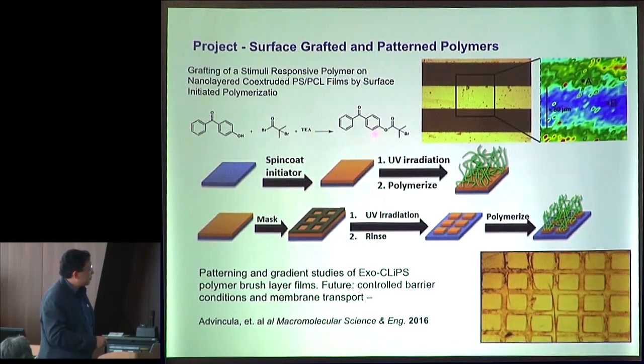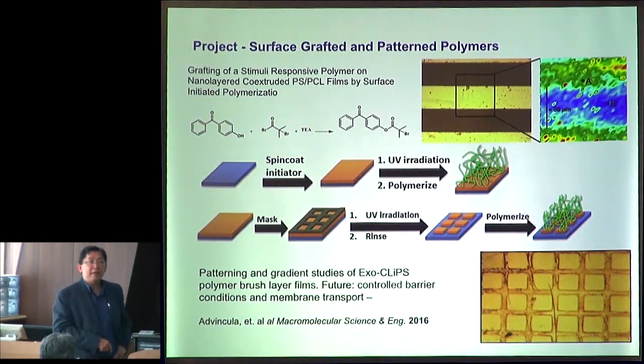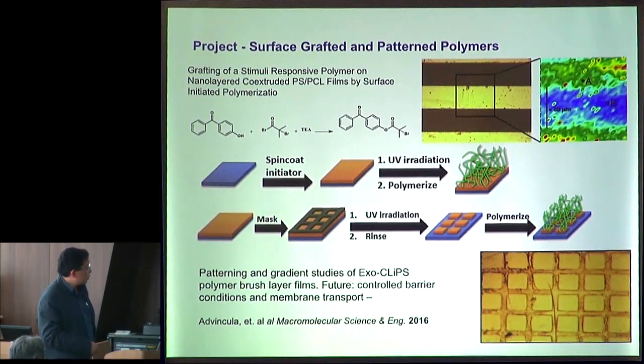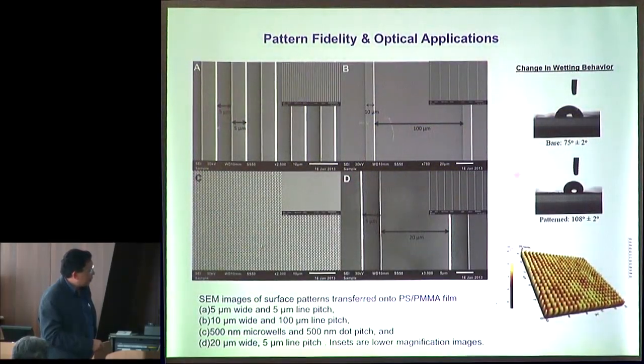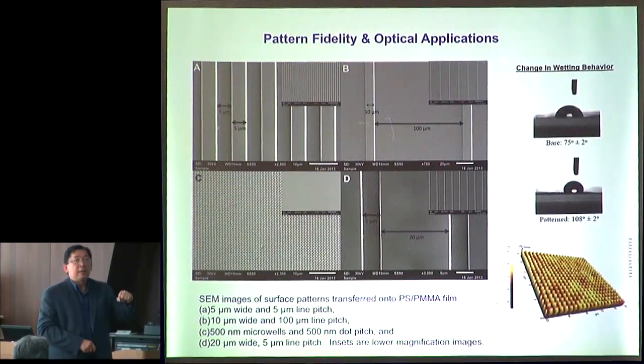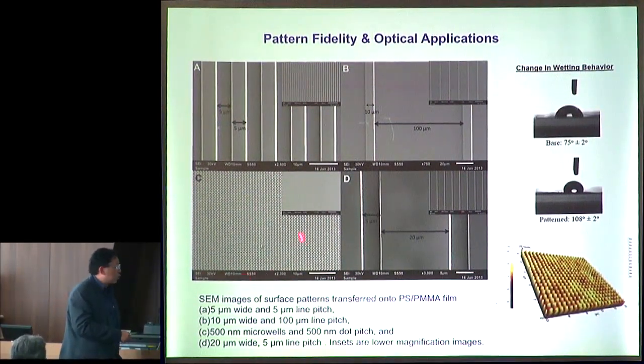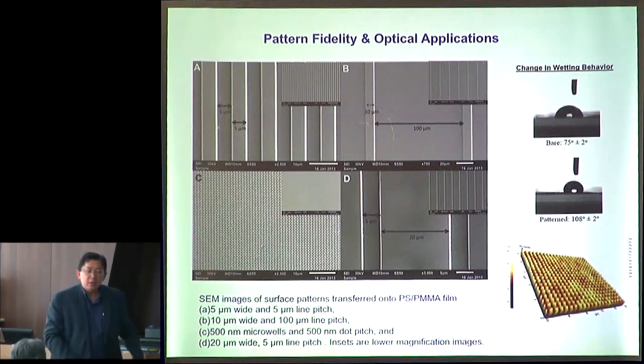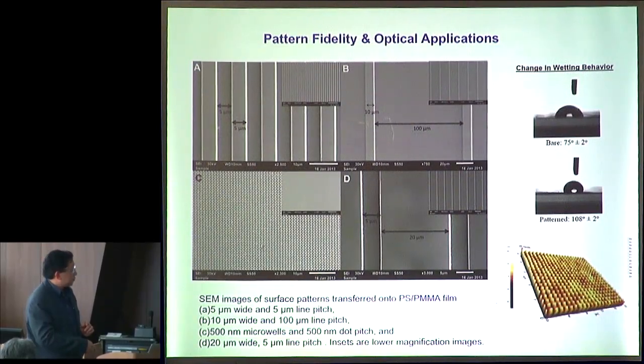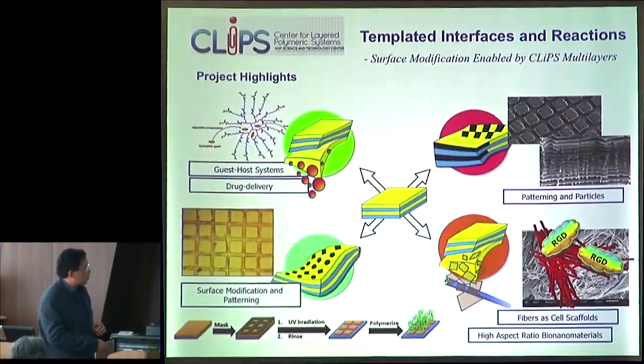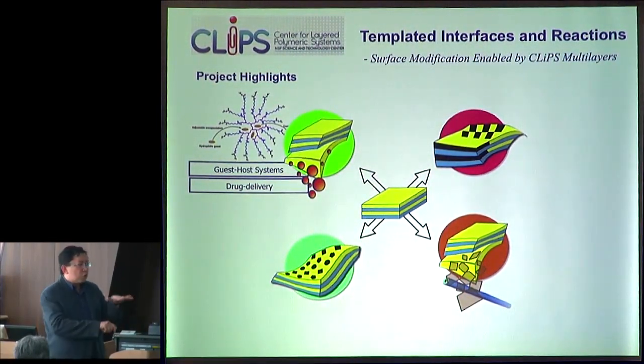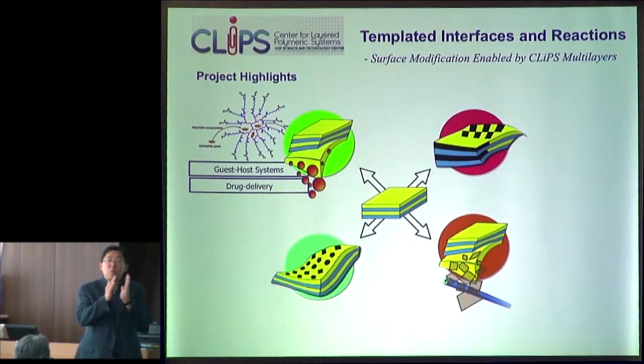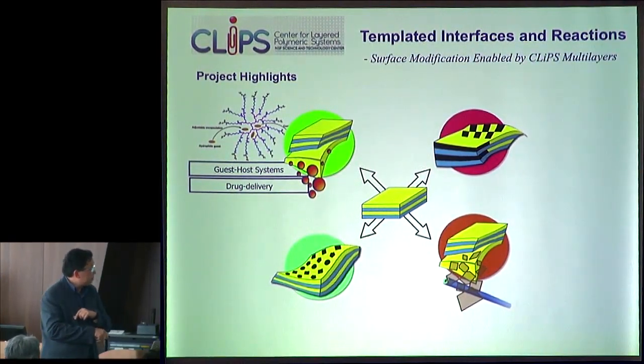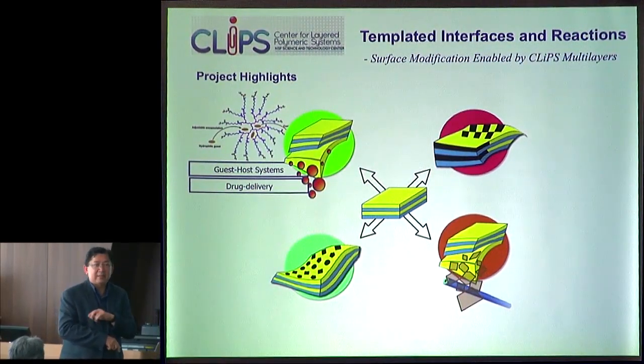Here, we grafted this benzophenone ATRP macroinitiator into patterns. We grew the polymer brush, and we found that we can distinguish the polymer brush behavior with the wetting as well as the functionality on the surface. Or we can prepare on top of those patterns a micro-imprinted feature, either as lines or dot structures that can have photonic features. In fact, those layers are essentially photonic band gap structures. So this type of layering, if you control the refractive index and the thickness, essentially controls the wavelength. Okay, and in fact, you can insert nanoparticles here. This becomes metamaterials. That's another story.